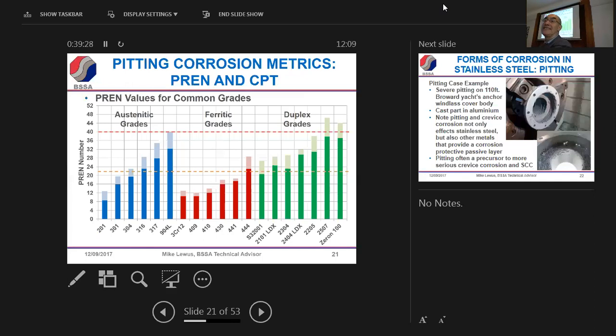So if you really want to take a sledgehammer to crack a nut, you could take 904L, which is classed as a super austenitic. You can guess whenever the word super is used, it just means it's got more of the good stuff: more chromium for corrosion resistance, more nickel for relative chemical inertness, more nitrogen for strength. So super is good if you can justify paying for it. Typically, we can rule out ferritics in the marine atmosphere. Duplex, you've got many to choose from in a marine atmosphere. The nice thing about duplex is it's typically twice the strength of a standard austenitic like 316, so you can get away with half the amount for a component that's going to bear the same type of load.